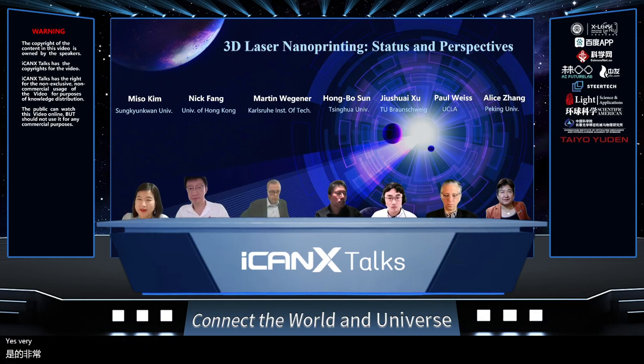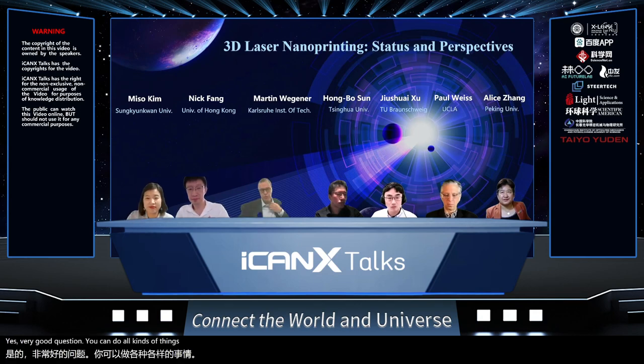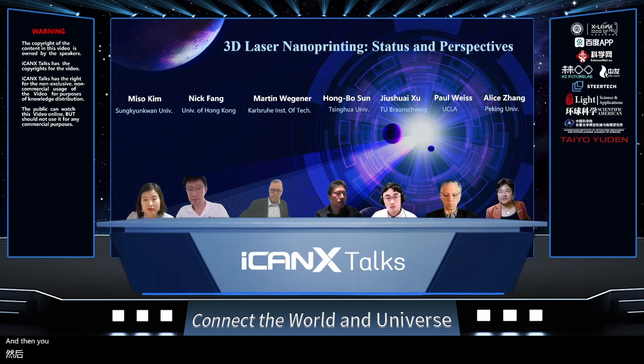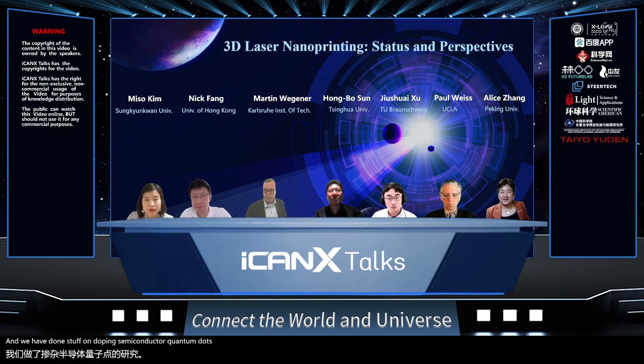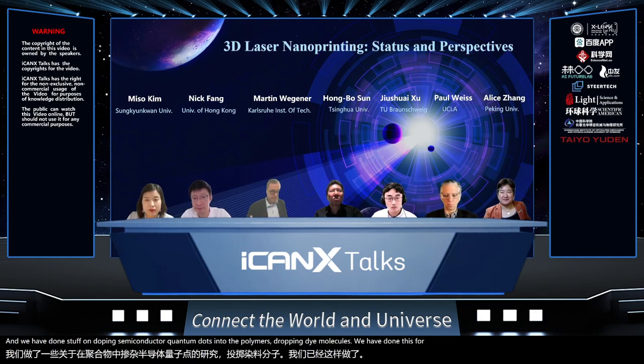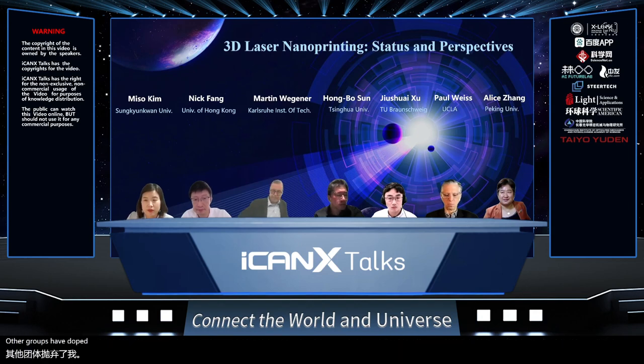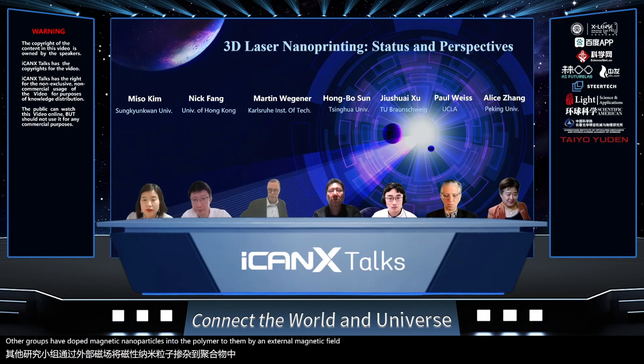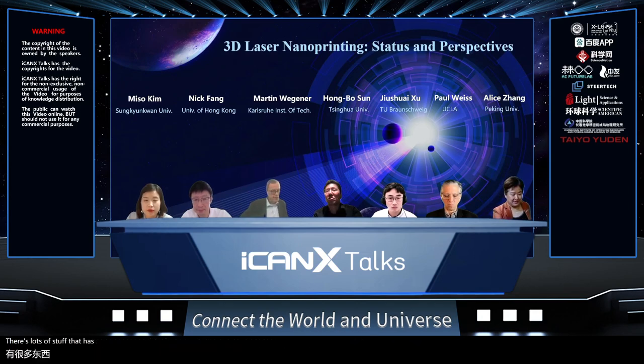Yes, very good question. You can dope all kinds of things into the polymer, provided the concentration doesn't get too large. Then you tend to get into trouble. If you keep it at a level of 1 or 2%, we have done stuff on doping semiconductor quantum dots into the polymers, doping dye molecules. We have done this for luminescent three-dimensional security features, for example. Other groups have doped magnetic nanoparticles into the polymer to then, via an external magnetic field, manipulate the structure. There's lots of stuff that has been done at the ETH Zurich in this direction, for example.